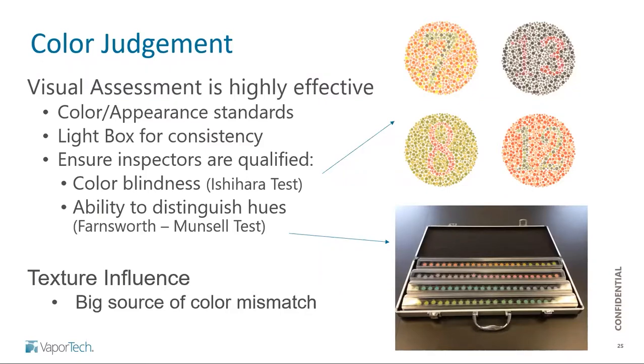For example, if you were to put the same parts in the chamber, apply the same color on something that's highly polished versus something that's got a matte surface, the polished surface is going to look much darker than one that has a matte or a diffuse surface. And that has to do with the diffusion of light and what's getting reflected back to your eyes. And it can be very tricky if you're trying to judge parts that may have different texture, if you've got different suppliers, vendors providing too much variety in texture that can really throw off your color. So just a word of kind of a pro tip from here: just be very cautious of that when you're judging color.